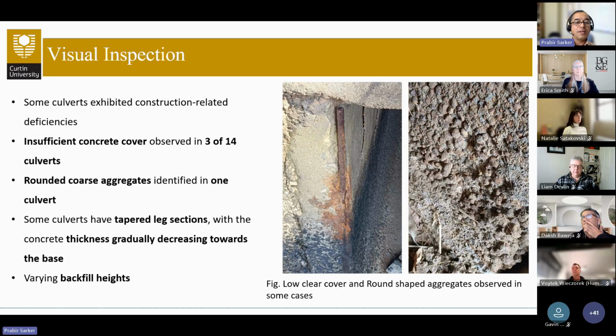Some culverts had tapered legs, tapered at the bottom, so the thickness of the culvert leg was high at the top but less at the bottom, gradually decreasing towards the base. Also the backfill heights in culverts varied - in some culverts the backfill height was very small, which can affect the load distribution of traffic to the culvert.